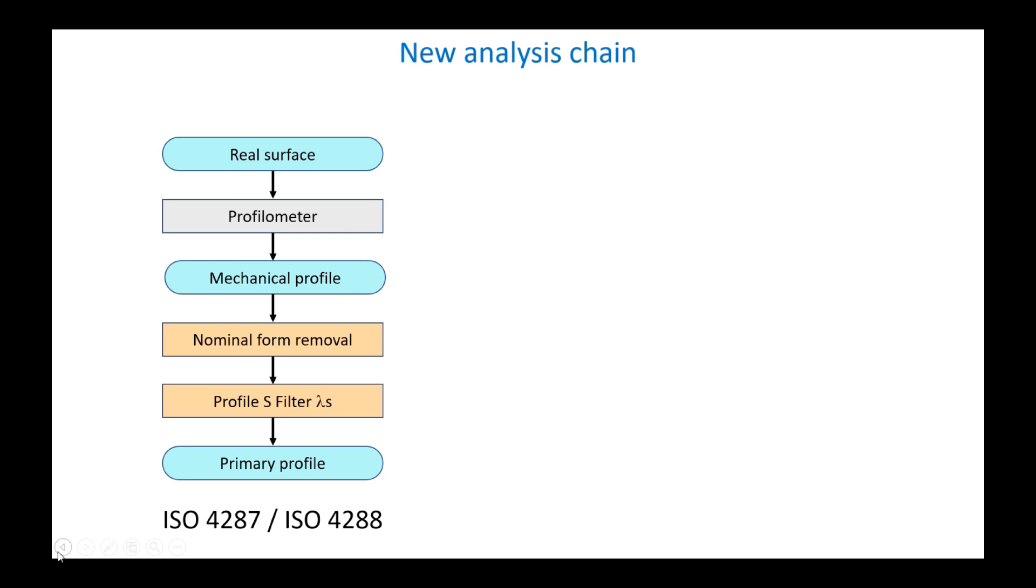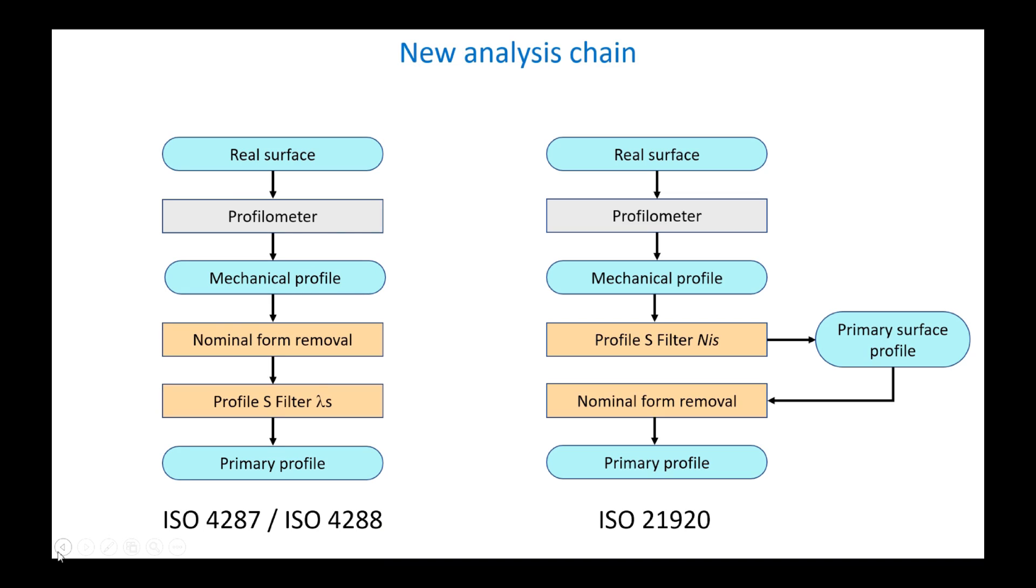In the new standard, these two steps are now applied in reverse order. We start by restricting the bandwidth before applying the form removal operation. On most profiles the difference will be quite small, but it is possible that on profiles with a large shape or geometric structures, the differences will be more noticeable.